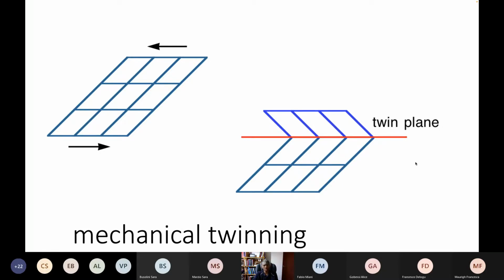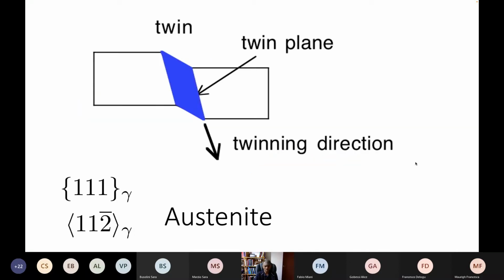And in the case of austenite, the twinning system, that means the plane on which the twinning happens, is the close-packed plane, the {111} type plane, and the direction in which the twinning happens, the twinning shear is directed.